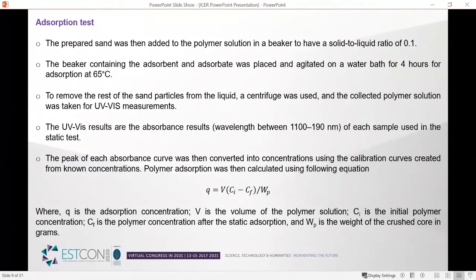So for the adsorption test, actually we mainly conducted our adsorption test by first mixing a specific amount of solution with the Marcellus sand at 0.1 solid to liquid ratio. And then we took this mixture and we inserted it into the water bath for adsorption at the elevated temperatures. And we left the solution for 4 hours, which was enough to reach the equilibrium, which will be explained later.